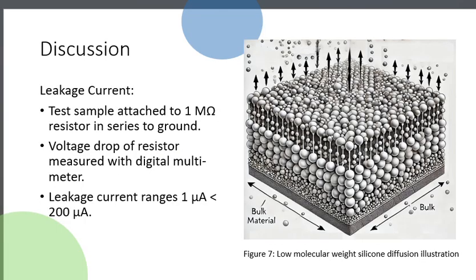Leakage current was measured using a circuit configuration where the test sample was connected to a 1 mega-ohm resistor in series with the ground. The voltage drop across the resistor was measured using a digital multimeter. Typical leakage current observed ranged between 1 microampere and 200 microamperes. Lower leakage current indicates better insulation performance and improved resistance against contamination.